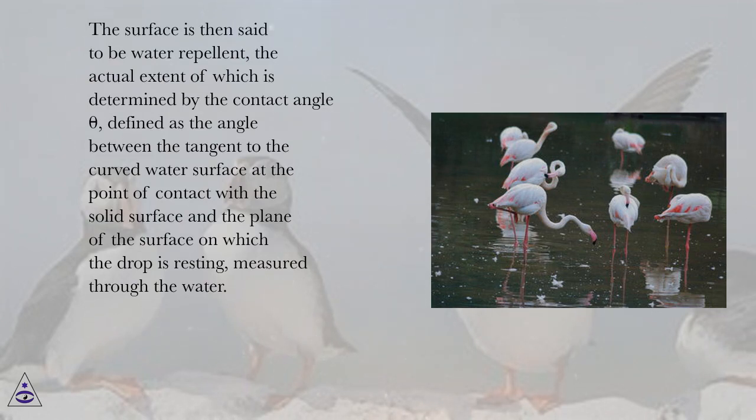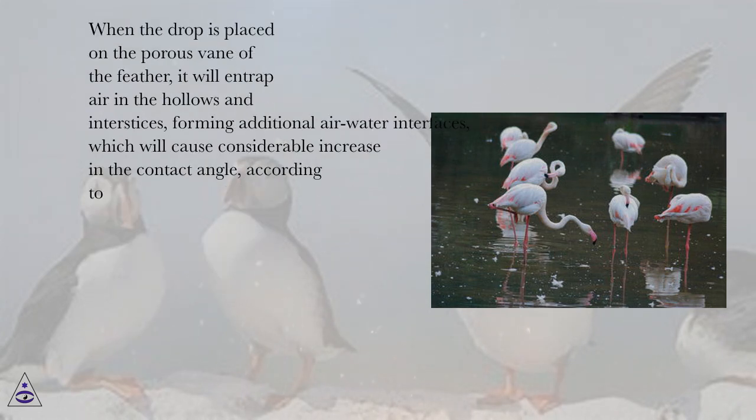the actual extent of which is determined by the contact angle theta, defined as the angle between the tangent to the curved water surface at the point of contact with the solid surface and the plane of the surface on which the drop is resting, measured through the water. When the drop is placed on the porous vane of the feather, it will entrap air in the hollows and interstices, forming additional air-water interfaces, which will cause considerable increase in the contact angle, according to